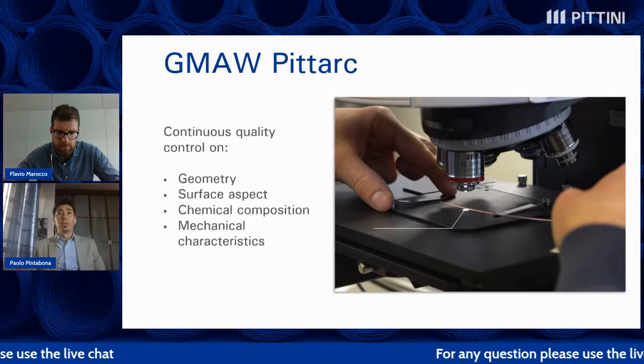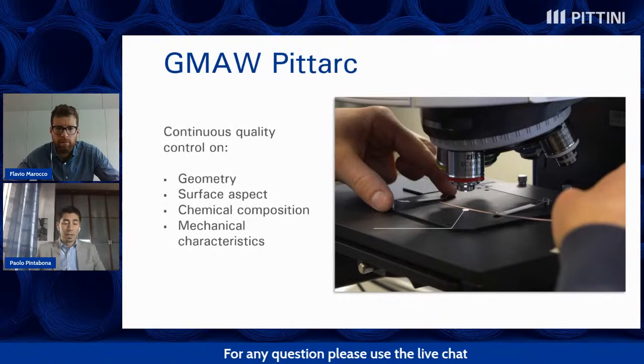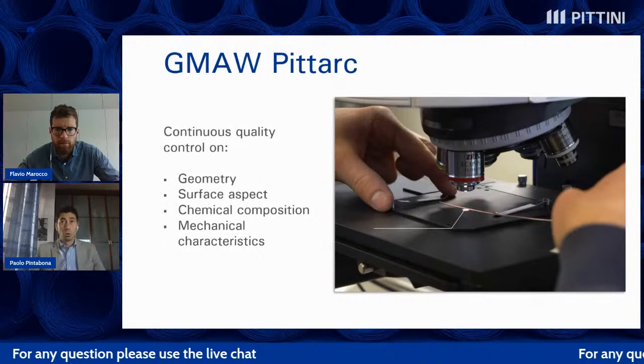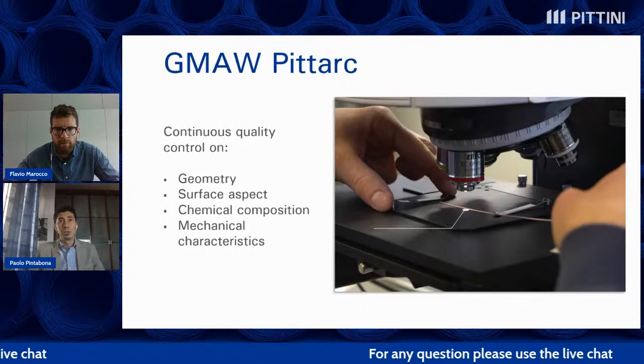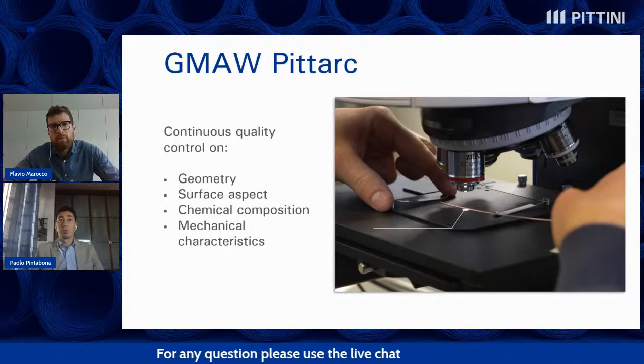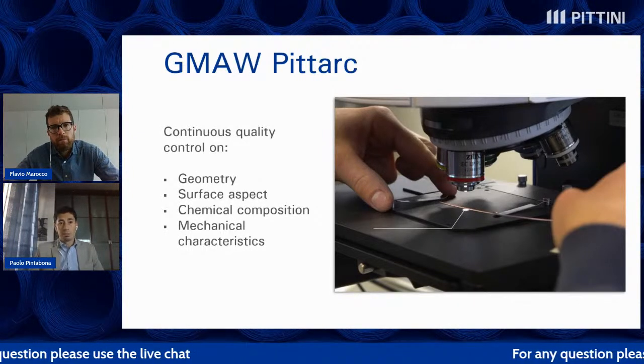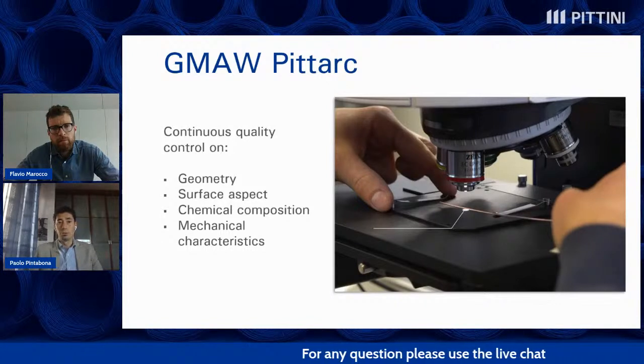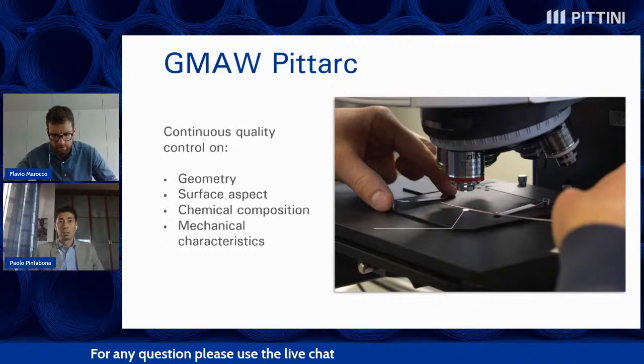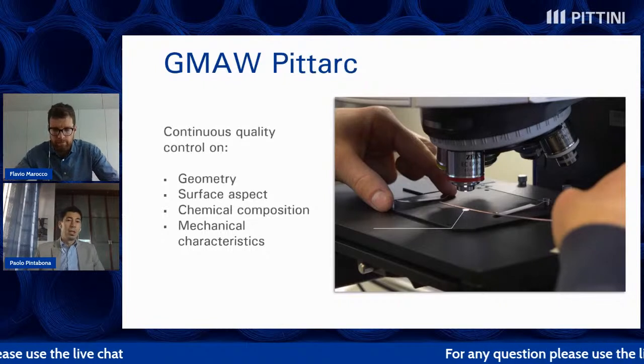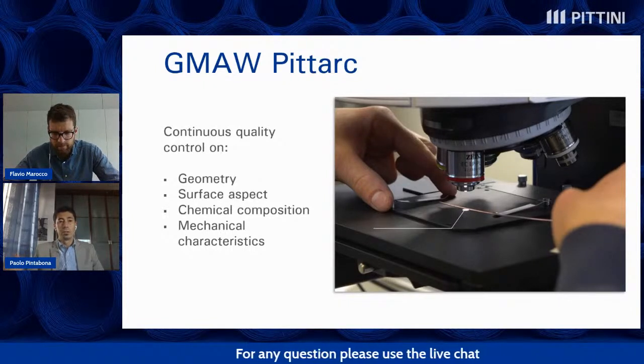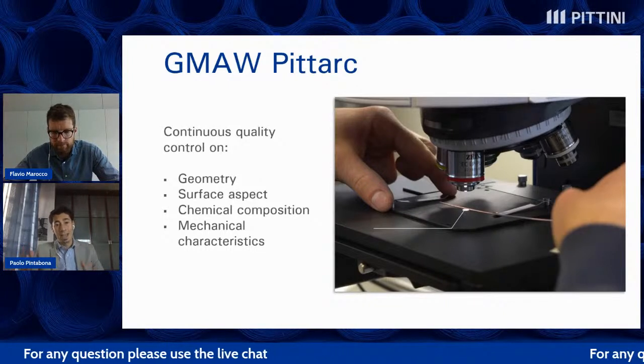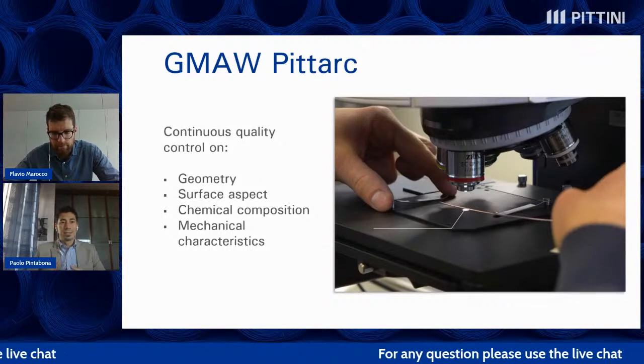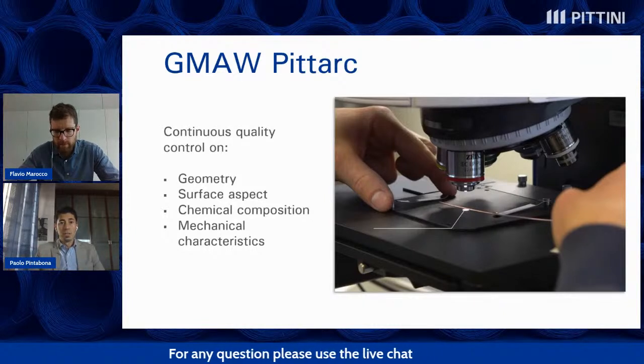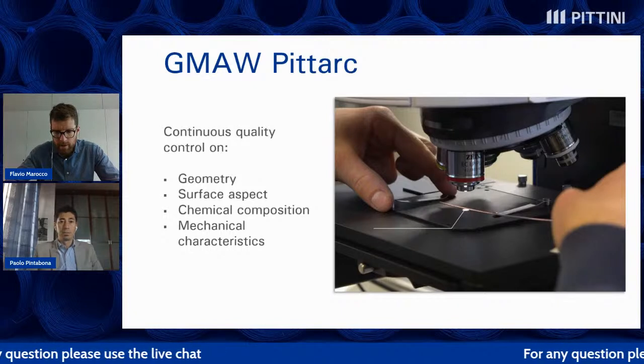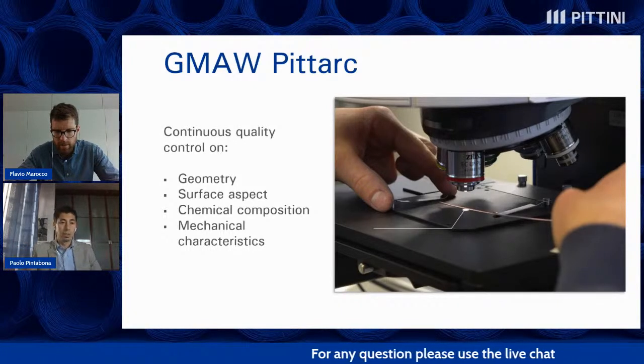I'm referring to the geometry, and so the diameter, the ovality, helix, and cast must be controlled using the proper instrumentation. One check has to be done for the surface appearance, and in this case, the samples must not show bruising or stains due to oxidation or dark spots due to chemical soaps left over. And concerning the copper-coated GMAW wires, the coating must be uniform and adherent to the surface, with the absence of cracks. A twist test is made as a proper control in this case.